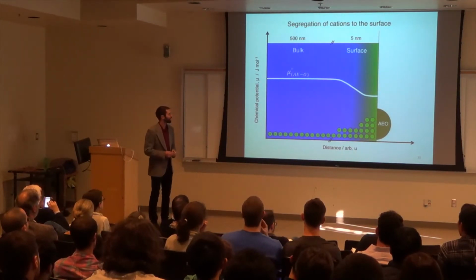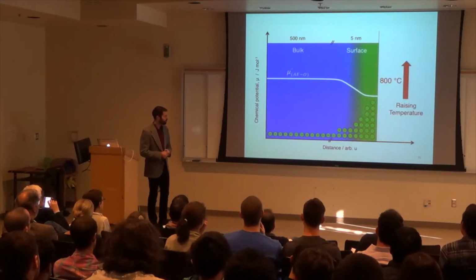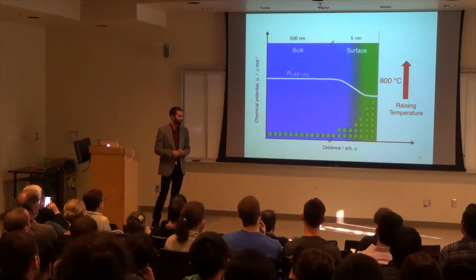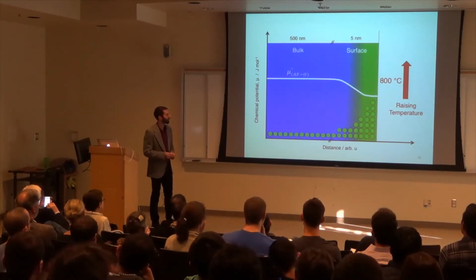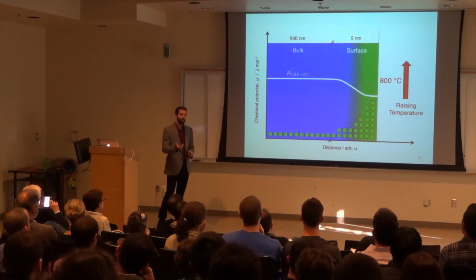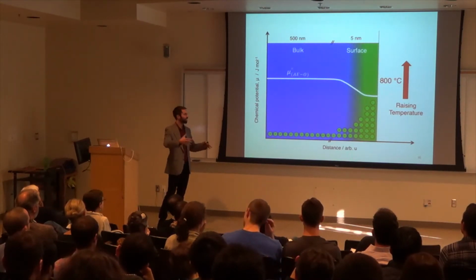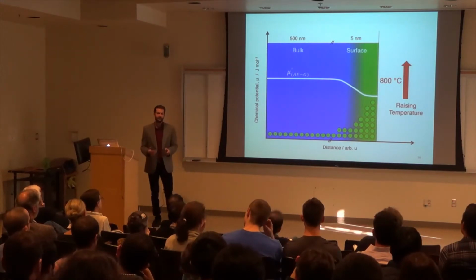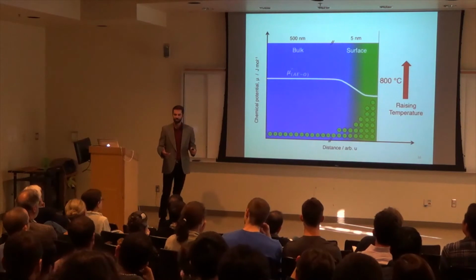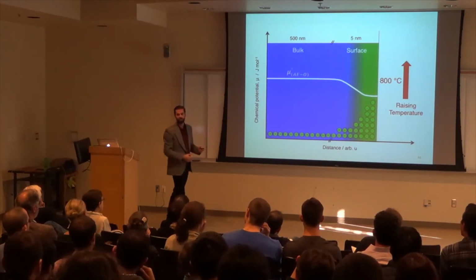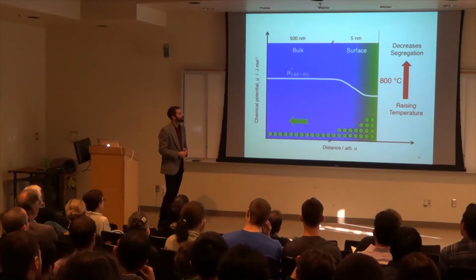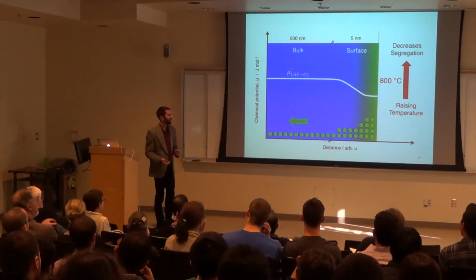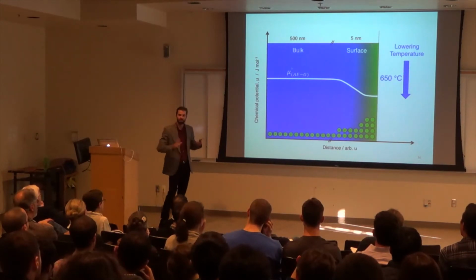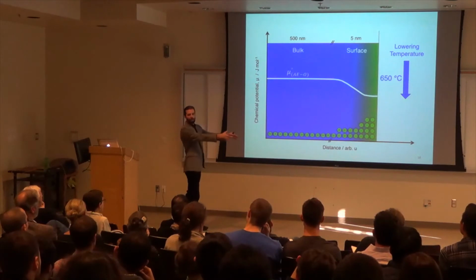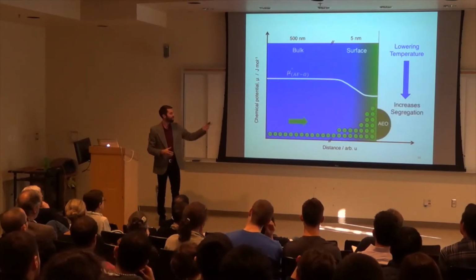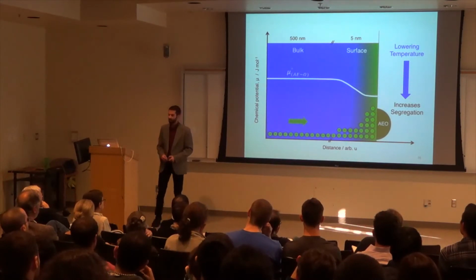So this is related to temperature because the entropic contribution to the chemical potential has a temperature dependence, such that when you raise the temperature, the entropy actually pulls these atoms back in, which is kind of contradictory to what you might think. This is because of configurational entropy, for those familiar with it. Basically it pulls them back in from the surface. But when you decrease the temperature, which is what people are trying to do to lower costs, segregation increases. The atoms might move a little bit slower to get out there, but you normally have entropy helping to pull the elements back in from the surface. So this leads to segregation and then precipitation of secondary phases.